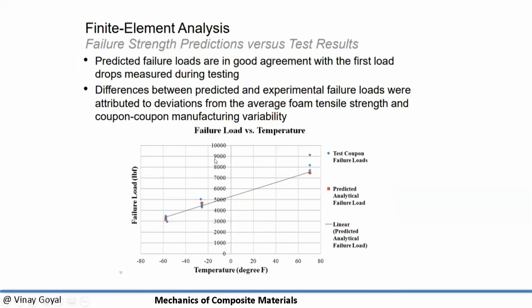Here you can see how the finite element analysis matches the strength prediction. And you can see here how the failure load matches really well from analysis to test all across. And you may ask why there's so much dispersion here. There's a lot of dispersion there because the failure mode here at room temperature was quite different from the one at cold temperatures. At cold temperature was foam failure, but when you go to higher temperatures, the failure was an interlaminar failure, a delamination failure between plies.